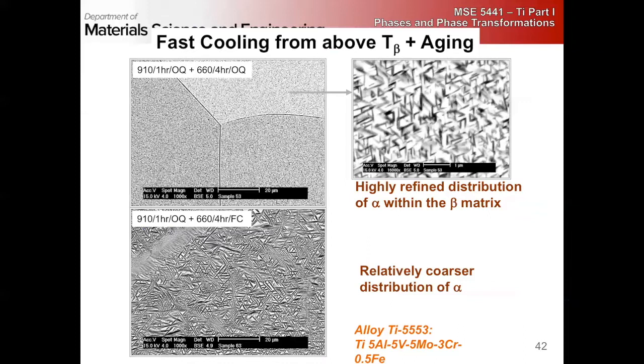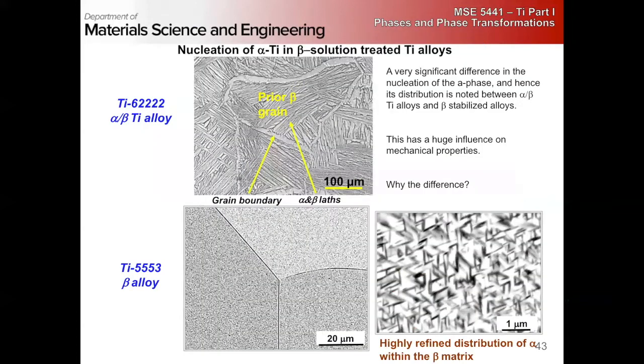similar to what we talked about in the alpha plus beta alloys. And then this slide, I believe I actually showed before. Oh, no, it was a different point I wanted to make on this slide. So here, notice the nucleation of the alpha phase in alpha plus beta alloys versus the beta alloys. For similar processing, notice we have a large amount of grain boundary alpha, allotriomorphic grain boundary alpha, that we don't have in the beta alloy. Here we see a well-developed colony structure with very narrow beta ribs.